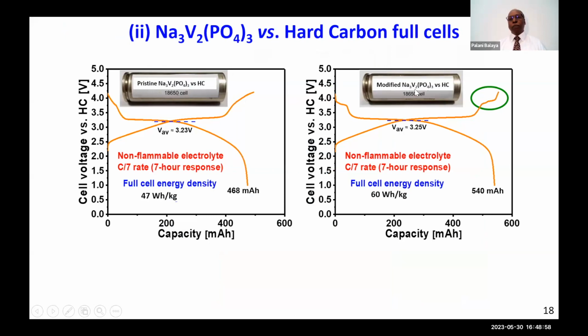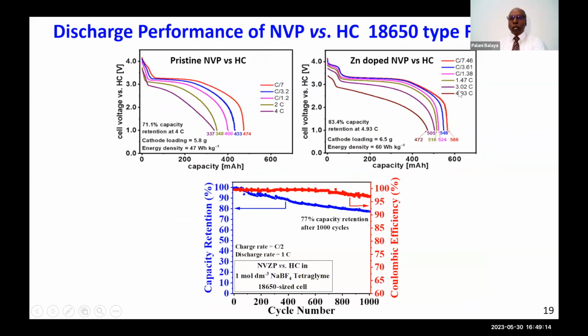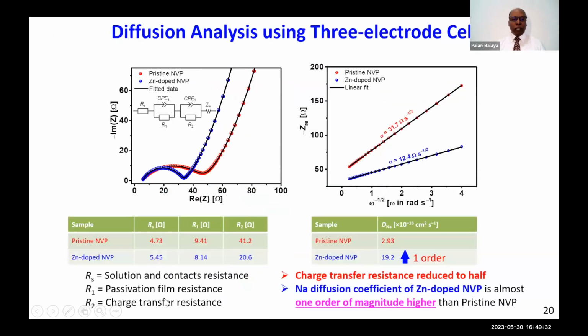This is modified sodium vanadium phosphate. We dope 10% zinc in the place of vanadium, modified sodium vanadium phosphate versus hard carbon. With the modification, one can see here the capacity goes up, the energy density goes up. Kilogram refers to the complete weight of the cell. And you can see with the zinc doping, the discharge rate can be as high as about 4 to 5 C. And we have shown pretty decent data, about 1,000 cycles retaining about 77% capacity with a 90% depth of discharge. Now, interestingly, what is happening with the zinc doping, as you can see here, is the charge transfer resistance is reduced to half its value. As a result, it also improves the chemical diffusion of the sodium within NVP.